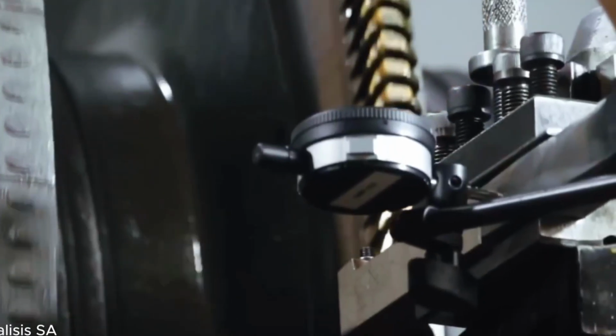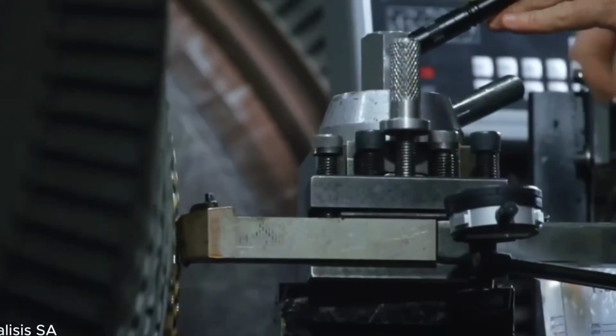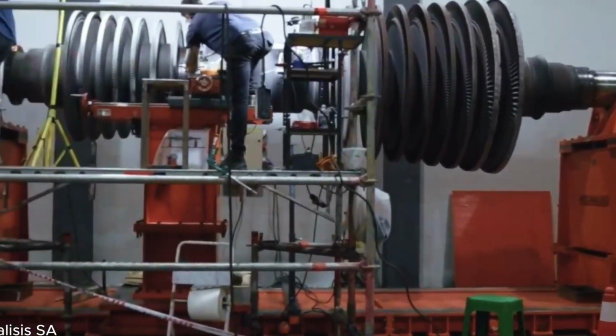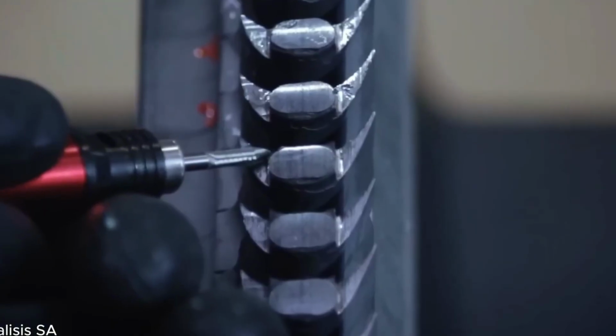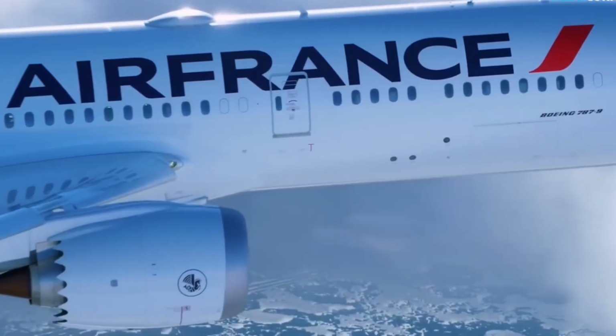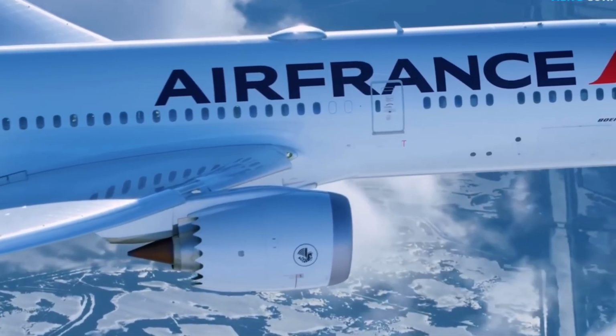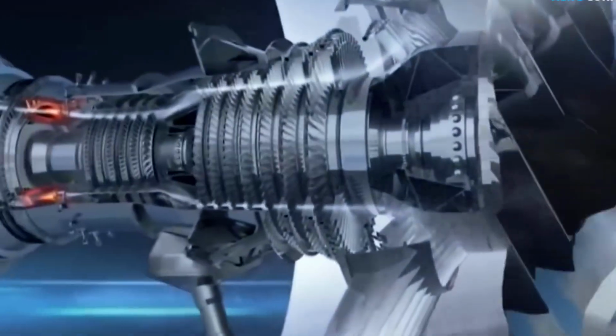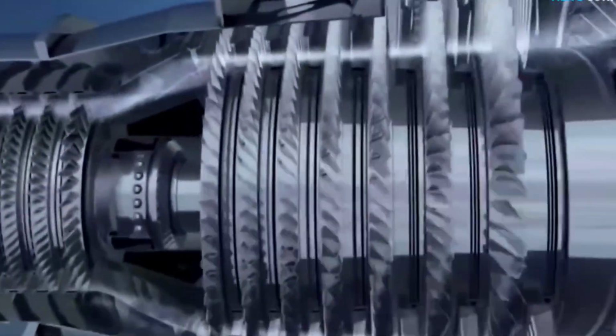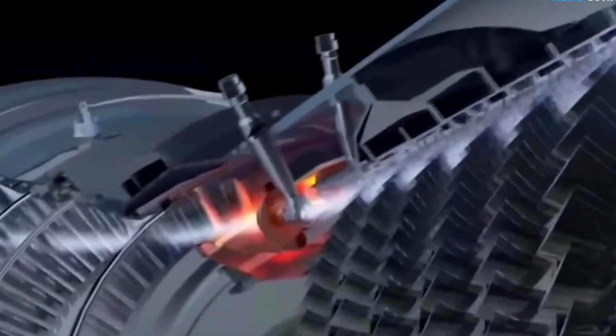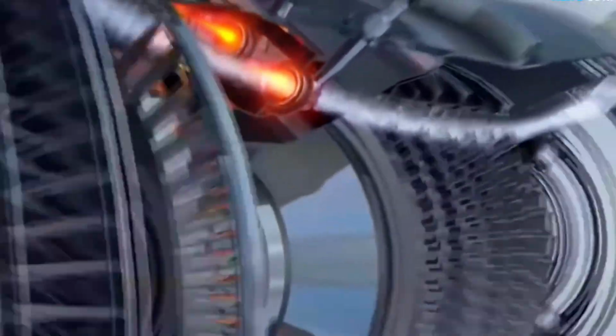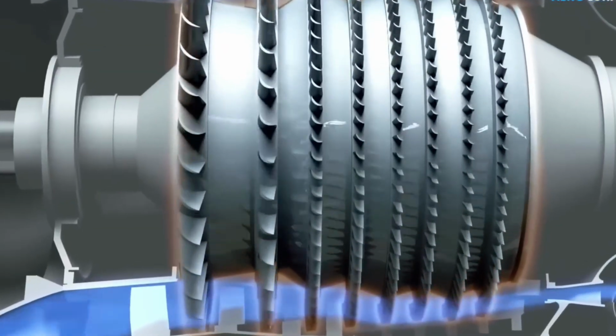Single crystal blades. Even the best metallic alloys are made up of millions of tiny crystals called grains. The boundaries between those grains are relatively weak zones. At extreme temperatures, atoms can migrate more easily through those regions, which promotes deformation over time. Engineers found a remarkable solution. Eliminate the grain boundaries entirely. Instead of manufacturing blades from thousands of interlocking crystals, they began producing them from a single continuous crystal. That's how single crystal turbine blades were born.